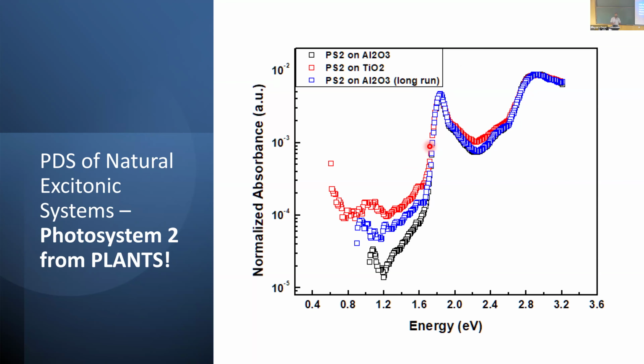This is visible because, as I mentioned earlier, I am only looking at non-radiative relaxation. Most physicists, if you see an exciton, relate it to radiative emission, right? But natural systems don't do that. If a plant were to absorb sunlight and emit light, it would have been fine, right? We would not be existing here. So they don't do that. In fact, most of the light absorption goes into non-radiative pathways, and that's where they make the food, all the reactions happen there. So because of that, you can see the excitonic peak even if it is non-radiative, and not so much radiative.